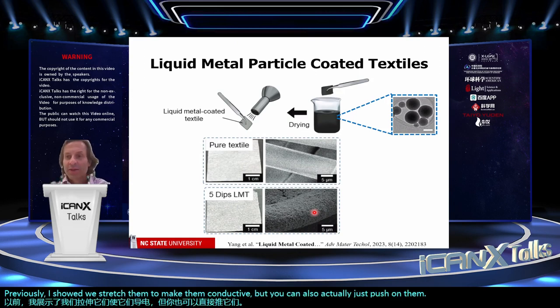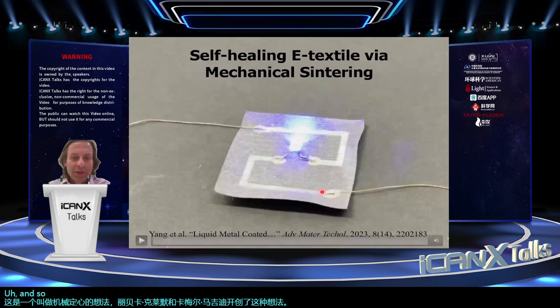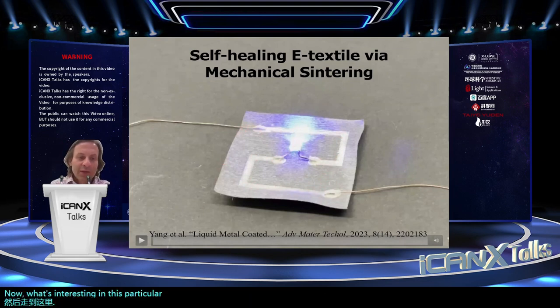Previously, I showed we stretch them to make them conductive, but you can also actually just push on them. This is an idea called mechanical sintering that Rebecca Kramer and Carmel Majidi sort of pioneered. We took this fabric coated with particles and squished it. We basically pushed on it and made a conductive circuit that lights up this LED and then goes over here. Now, what's interesting in this particular case is that, again, there's particles even over here.